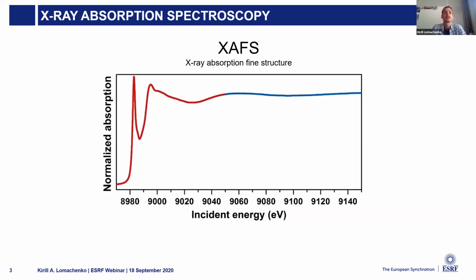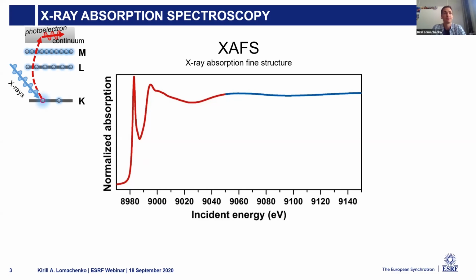So the essence of the method is analyzing the dependence of the X-ray absorption coefficient on the energy of incident X-rays. Usually this dependence is pretty smooth, but in some particular regions, you can have very sharp steps, sharp jumps that we call absorption edges. They appear when the energy of incoming X-rays exceeds the binding energy of electrons at particular atomic levels, core levels of particular atomic species present in the sample. And that's what makes the method element selective.